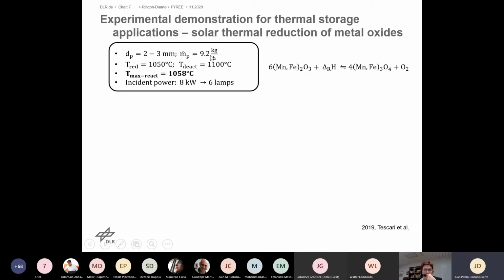The mass flow that we used was about 9 kilograms per hour. And for this material, we had a reduction temperature of 1050 degrees, but we had to be careful because if we overheated the material over 1100 degrees, the material deactivated. So in our experiments, we reached a maximum temperature of 1058 degrees. And for that, we used 6 lamps of the solar simulator, which is about an incident power of 8 kilowatts.